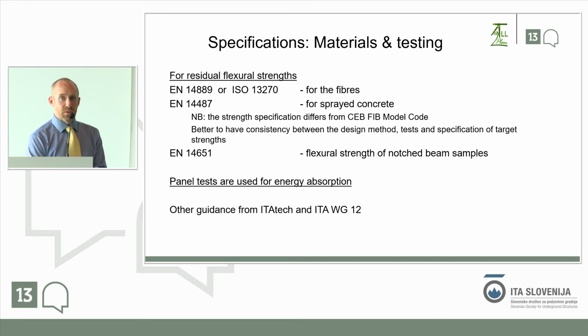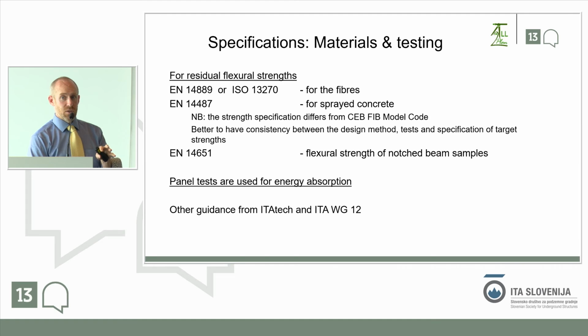Specifications. So the good thing is we have quite a lot of information on that. If we're looking at residual flexural strengths, it's probably best to be using the notched beam test, 14651. Panels, you can use RDP, the round determinate panel, or square panels, which we discussed a lot yesterday. If you look on the ITA website, you'll find that we've produced several reports. There's 2 reports on precast segmental linings, which has a lot about general design of fibre reinforced concrete, and then also in working group 12, we've looked at sprayed concrete as well.